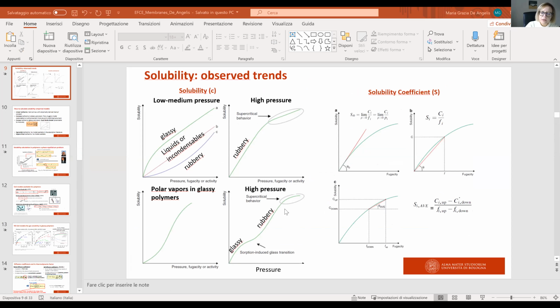Okay, so here what you see is that the solubility isotherms around the critical pressure of CO2 flatten out. This is because the CO2 starts to behave in a liquid-like manner, and liquids are insensitive to pressure. So the solubility of CO2 becomes less dependent on the pressure, because the behavior is liquid-like. So the curve flattens out.